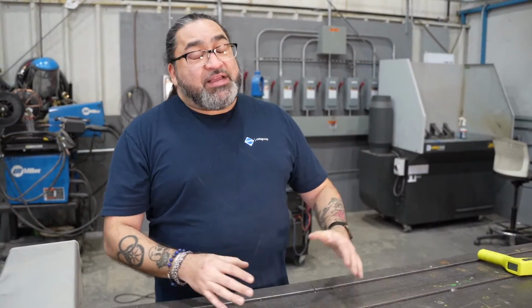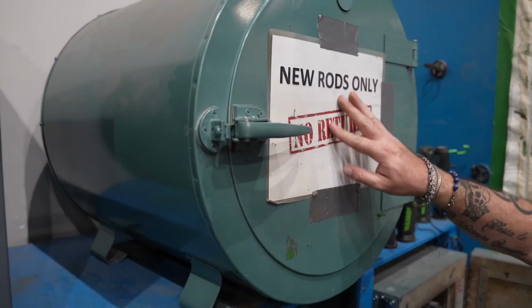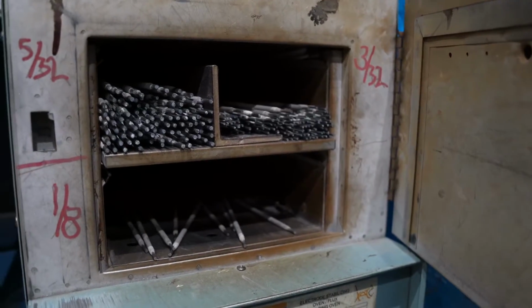Sometimes on the work site, things happen. Electrodes are left out, they get cold, they get wet, or you find a box that's been opened and not put away properly. What can you do? Well, under W59, you can recondition or rebake the electrodes. By rebaking them, you'll have to put them in an oven at above 230 degrees Celsius for a minimum of 2 hours. After that, they can go into a normal rod oven where they'll be kept at over 120 degrees Celsius. By doing that, you ensure that all hydrogen and moisture is removed from the electrodes. Just a quick note, if the electrodes are rebaked, you are only allowed to do this once.